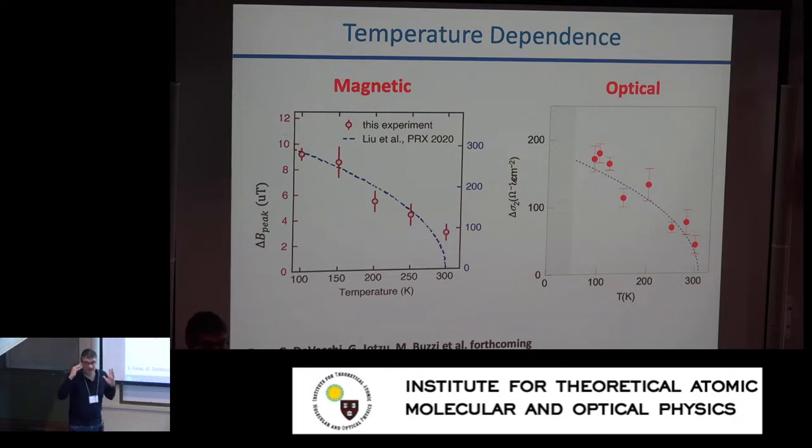In the light-induced state, you generate a transient superfluid density that is the same as the zero temperature superfluid density in the same material, and you get an expulsion of a magnetic field that is too large to be anything else, and is larger than the diamagnetism that you find in the same material field cooled.